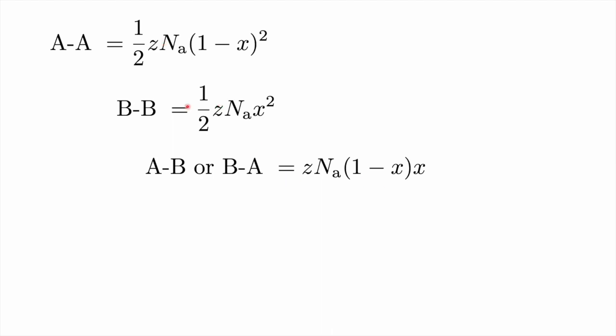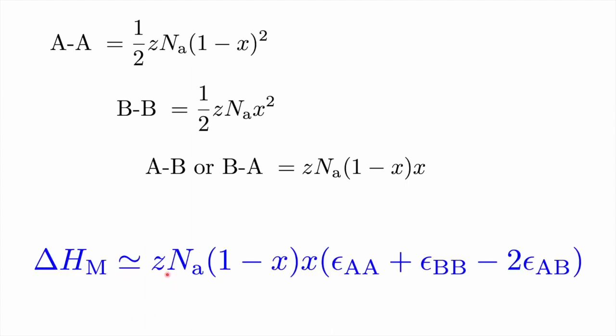If we knew the energies of each of these bonds, then we could work out an enthalpy of mixing. And that energy is simply given by the coordination number times the Avogadro's number, because we're looking at a molar quantity, the probability of an A atom and a B atom multiplied by the energies of the bonds. So this energy represents what happens when you break an AA bond and a BB bond and create two AB bonds. So it's the energy of the AB bonds less the energy of the original AA bond and the BB bond. So the enthalpy of mixing depends on this. And this is a term which we can obtain experimentally or by calculation.